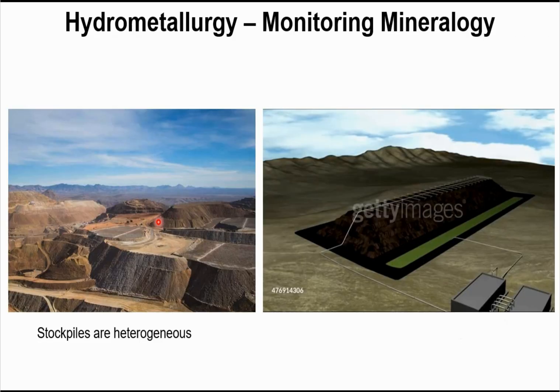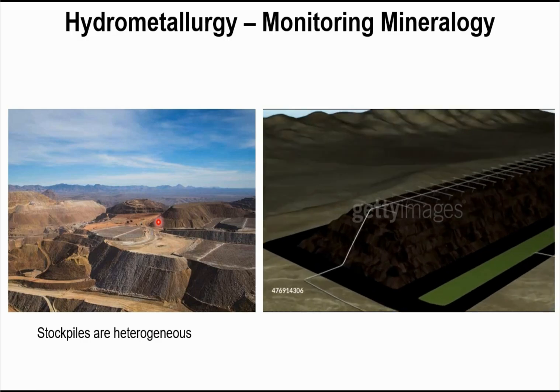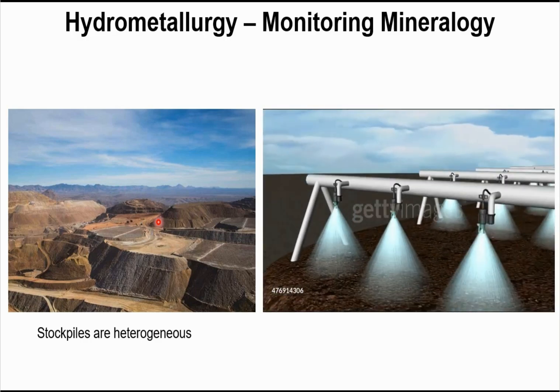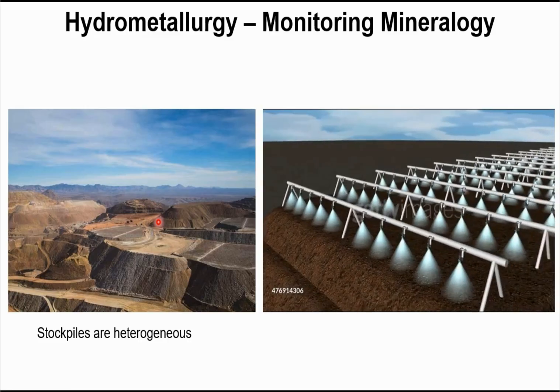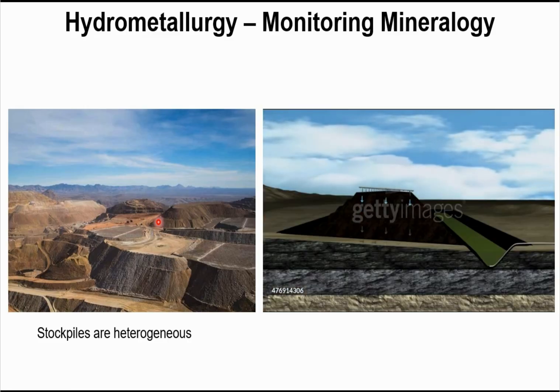So last couple of slides here. On the left is a heap leaching operation in Arizona. About 20% of the world's copper comes from heap leaching, 80% from smelting. And heap leaching, it involves, as the video on the right shows, spraying what we call a lixiviant on top of a pile of disaggregated crushed ore. The lixiviant flows through the pile, chemically reacts with copper sulfide, copper iron sulfide, and copper oxide minerals. And then it's collected, and what we call the pregnant leach solution, that is then electrolytically refined and the copper is purified.